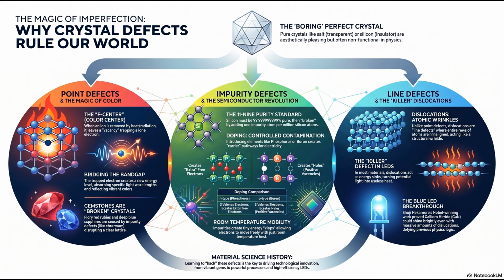It was the microscopic equivalent of a shredded, puckered rag. Based on the physics we just spent 20 minutes discussing, that material should have been completely dark. Any electron injected into that lattice should have instantly fallen into a killer defect, vibrated the crystal, and died as heat. By every known law and heuristic of solid-state physics at the time, his device should have been a complete catastrophic failure, a useless hot rock.